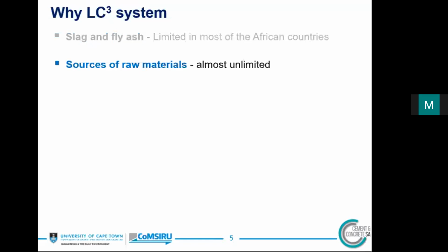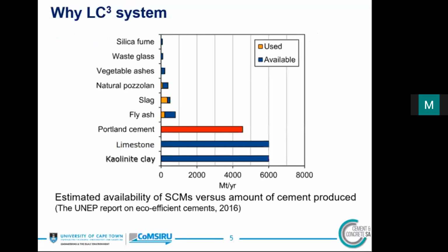And then number 2 is about the availability of these materials. Now, sources of LC3 raw materials are almost unlimited. This figure here shows the estimated availability of supplementary cementitious materials versus the amount of cement produced globally. It's clear from the figure that we have limited amounts of slag, fly ash, and all these other materials, but we have huge amounts of limestone and kaolinite clay.